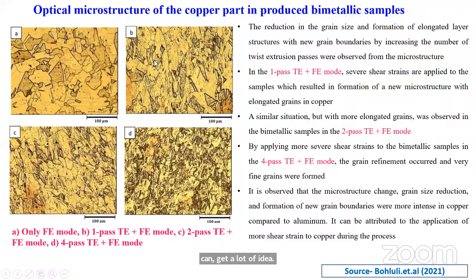Then after the twist extrusion pass, you can see the orientation of the grains in the direction of the twist. With further twist extrusion, you can see the grains are oriented in several directions. Still, the grains are large in size. After more passes and the forward extrusion process, you can see the grains are homogeneously distributed throughout, from the corner to the center of the samples.